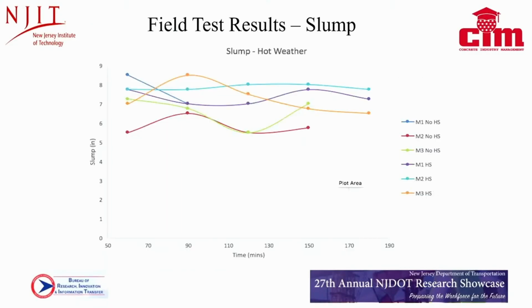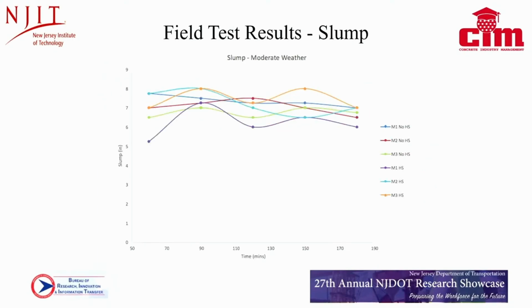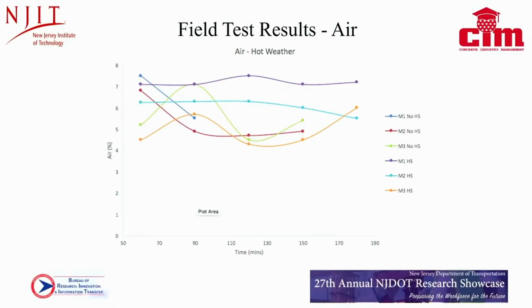So we have a number of graphs. This one speaks of slump. You have mix 1, 2, 3. Remember mix 2 and 3 was with fly ash and slag. And the slump, it didn't vary much except in the beginning. But as you can see, it pretty much was stable throughout up to 180 minutes. This one represents the air percentage. See, we were able to keep it fairly constant, around 6%.